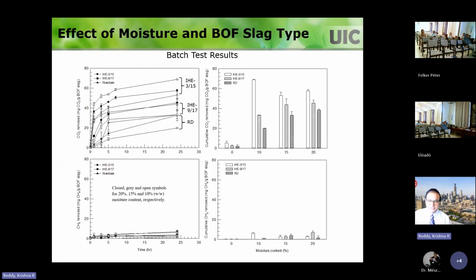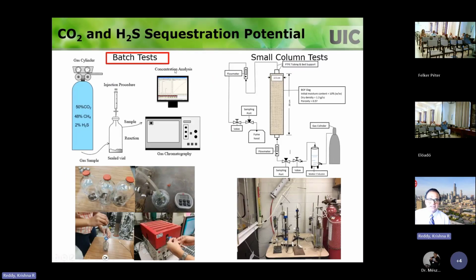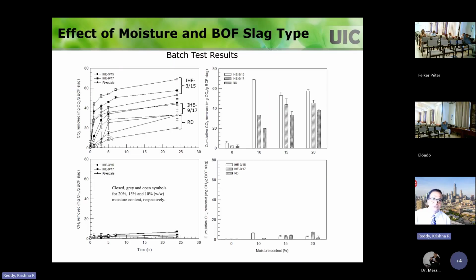If you do the batch test, basically we're taking the slag and we're injecting the CO2 and measuring the concentrations with time. So if it is sequestering, CO2 concentrations will reduce, right? And then we can calculate with time how much CO2 is removed. So this shows the CO2 removal for the 3 slags that we looked at. So you can see it removes quite a bit, right? And we injected a CO2 and methane mix, but nothing happens to the methane. Obviously, in the cover system, the biochar amended soil would have taken care of all the methane, and then only CO2 would be coming into this layer.